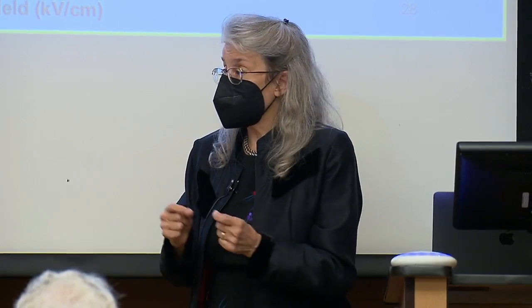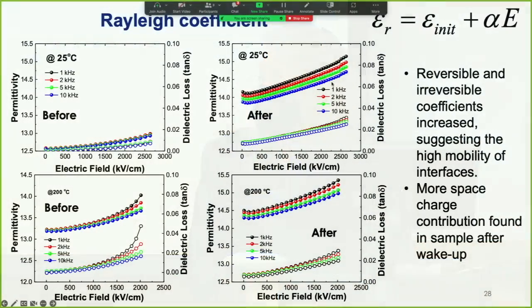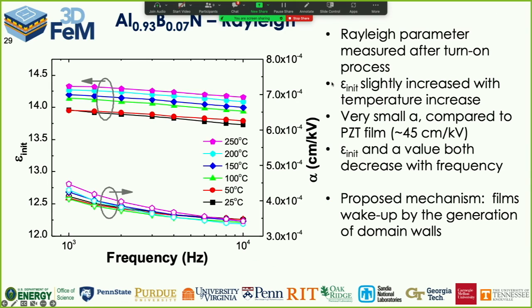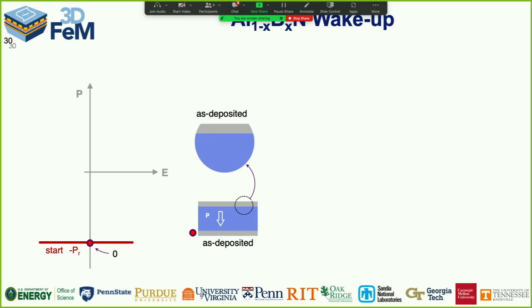Once we built domain walls into the solid by waking the material up, the basic permittivity went up, and the slope of the permittivity as a function of the amplitude of the AC electric field goes up. And we've been able to map that as a function of temperature and frequency. And we believe this is the real way that this family of materials wakes up. We grow them in a single polarity. So in our particular case, the aluminum boron nitrides all grow poled down. So you start with a material with no domain walls in the poled down state.